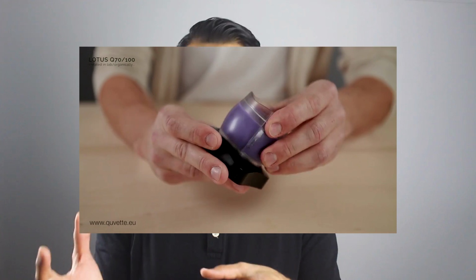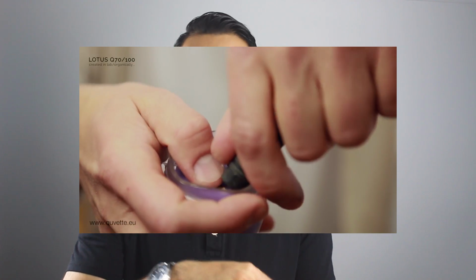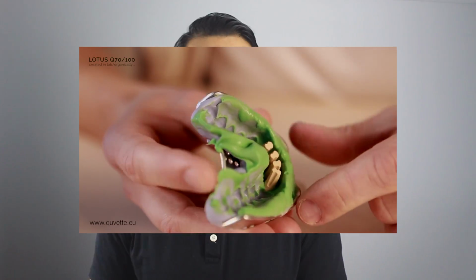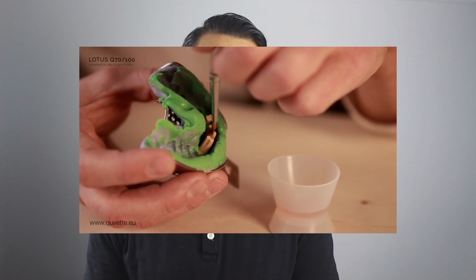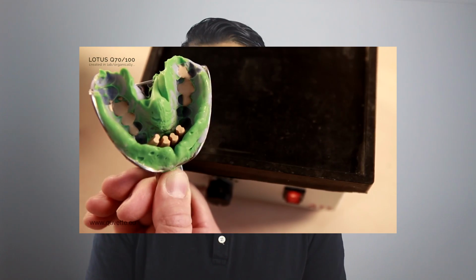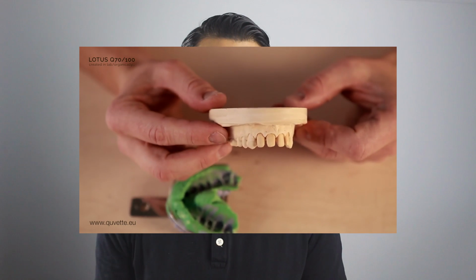The phosphate-bonded refractory die materials are used in a different way to the investments. A duplicating impression of the working die is made, usually using a proprietary material. The mixed refractory die material is poured into this impression and allowed to set. It is then removed from the impression and consolidated by firing at about 1000 degrees. The surface is then coated with a thin layer of glaze and the die refired at a slightly lower temperature, for example at 970 degrees. The surface glaze helps to prevent moisture from the porcelain from being soaked up into the porous die material.